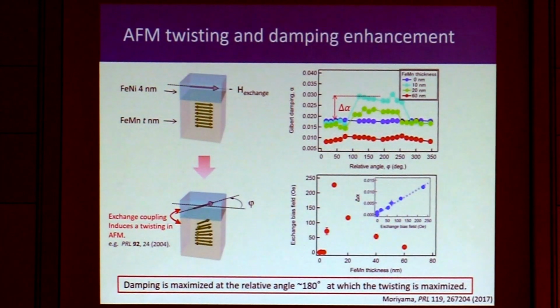So what we have done is, again, this is an iron manganese permalloy bilayer. We just create an exchange bias in a certain direction. And when we measure the Gilbert damping, by the way, the Gilbert damping is measured by ferromagnetic resonance and the linewidth, and from that we can measure damping. For the measurement, we just apply the external magnetic field by relative angle phi, and we take the Gilbert damping as a function of the relative angle phi.